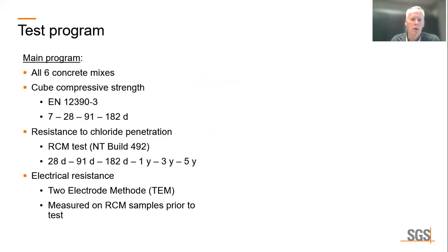Now let's take a look at the test program. First, we have the main program, which was performed on all 6 concrete mixes. We first measured the compressive strength development up to half a year. And then we measured the resistance to chloride penetration by the rapid chloride migration test following NT Build 492.